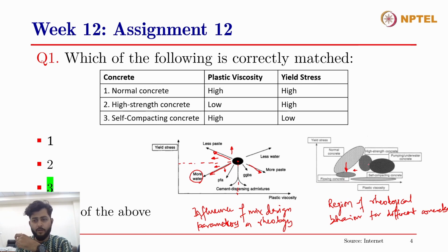Similarly, in the case of high strength concrete, a relatively higher viscosity in the concrete mix, but similar yield stress. The yield stress is similar, but the viscosity is increased. And this is exactly why I explained to you the more paste case. When you increase the paste content, the viscosity increases and the yield stress is more or less similar or it decreases a bit. In the case of high strength concretes, as compared to normal concretes, you are essentially increasing the cement content in the mix. When you increase the cement content, the viscosity in the mix will also increase, even though the yield stress is not affected much.